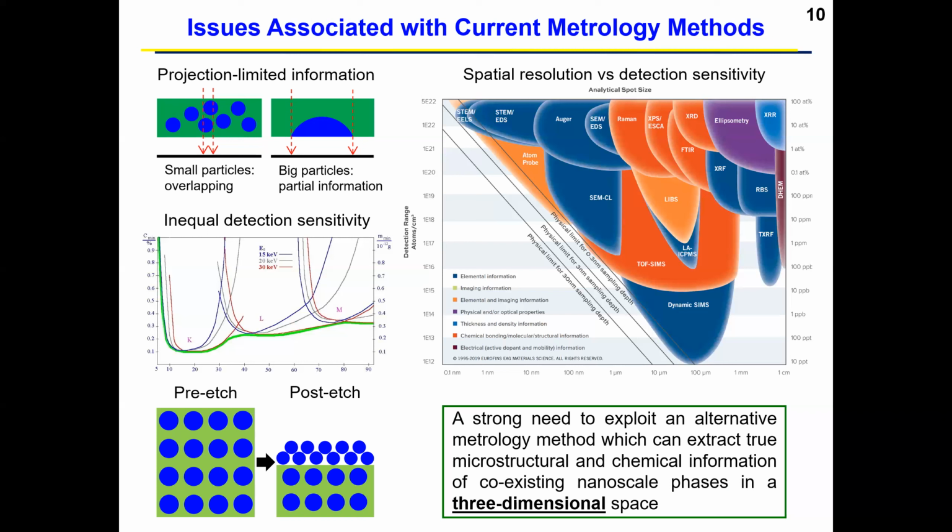Also, XEDS and EELS provided by TEM have atomic number dependent detection sensitivity. In the well-known plot of the minimum detection level, you can see why those with low atomic numbers would have to have a large quantity to be barely detected, which means when you have a low concentration of those such as boron or lithium, XEDS and EELS have intrinsic limitations.